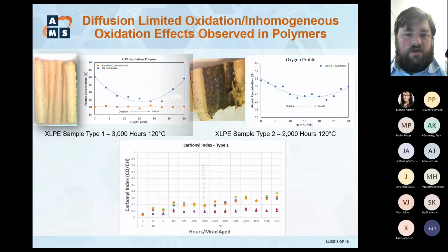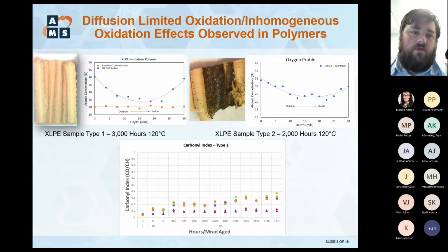So those are the type 1s, 2s, and 3s that I mentioned. The data I show on the left is a type 1 material, so that's just a bare insulation aged in the oven. A type 2 on the right is one of the cable samples. You see the same type of discoloration pattern, although the lighter region in the middle is whiter in that one, indicating potentially more significant diffusion limit oxidation effects and inhomogeneous aging effects. And there's a difference in the oxygen profile. You still see that parabolic relationship, but keep in mind that because of oxygen consumption by the jacket material, we're actually seeing more significant inhomogeneous aging effects from an oxidation standpoint in these materials, because the amount of oxygen getting to the insulation through the jacket and other components in the cable is limited.